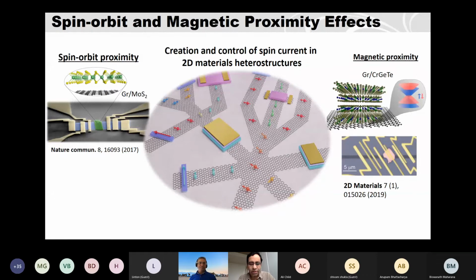Yeah, I believe similar considerations also apply for studies like X-ray absorption spectroscopy, like XMCD. Whatever studies I see with XMCD, people are now studying these magnetic materials, and it's mostly on bulk magnets, not monolayers. For monolayers, most of the studies are with MOKE because it's easier, and if it's an insulator, then that is the only technique. But with graphene heterostructures, one can also detect with the proximity effect.